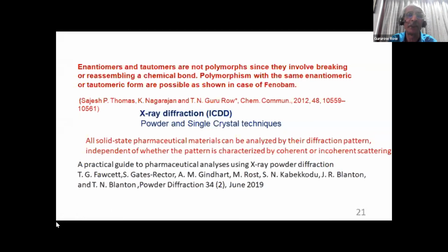So what it tells essentially is the key technique in all these is the use of X-ray diffraction. And with the big amount of data that is already available in the ICDD database, it is very, very critical to use the X-ray diffraction data to the advantage of looking at polymorphic modifications. We can look at the existing polymorphs if we want to make a new polymorph and then evaluate them. X-ray diffraction would aid in all these very, very uniquely.